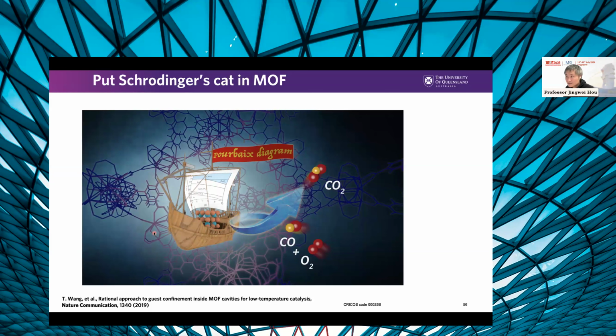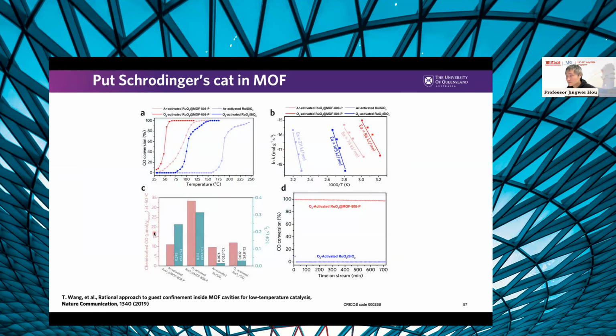In this case, we can use a Pourbaix diagram to help us synthesize metal oxide within the pores of the MOF. That's actually making the MOF much more chemically, much more catalytically reactive. So again, this is a very basic figure, not going into too much detail, but you can see that compared with the catalyst embedded on silicon oxide, which has been regarded as a very classical system, the ruthenium oxide embedded in the MOF 808 is much more efficient.